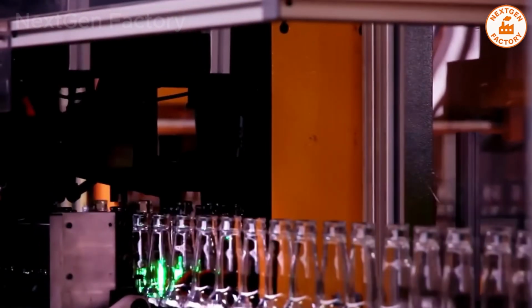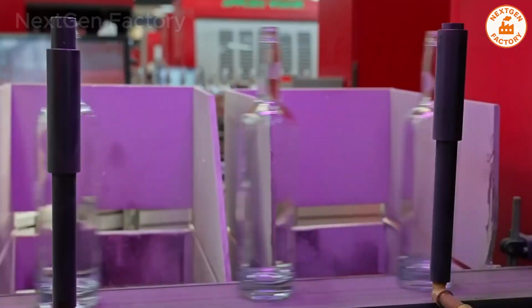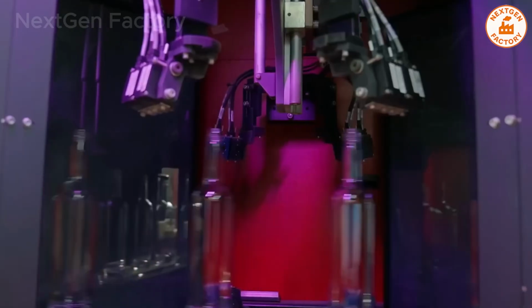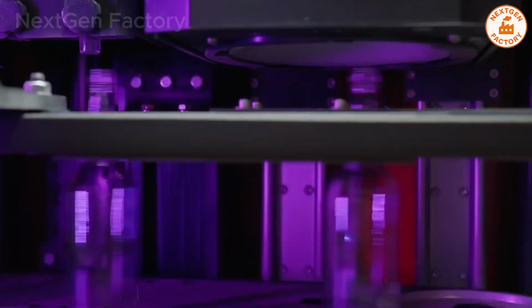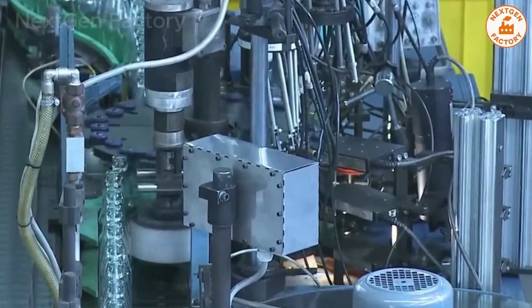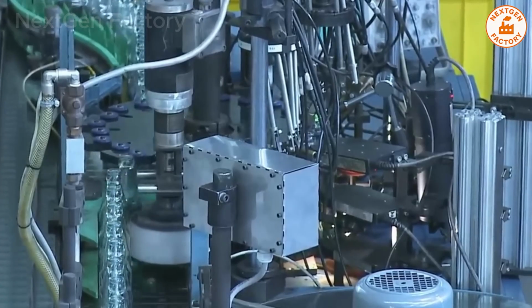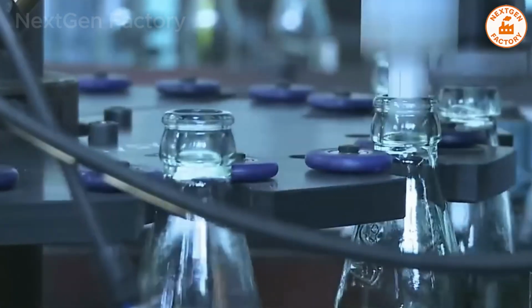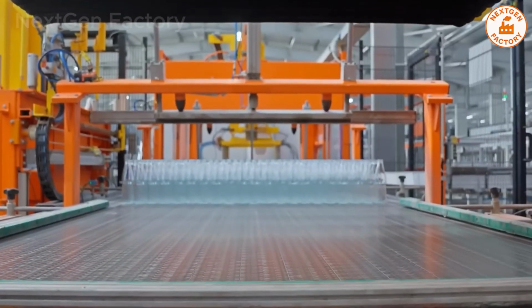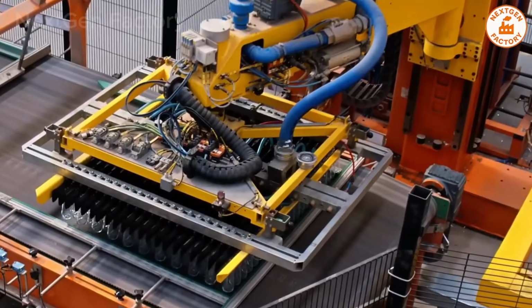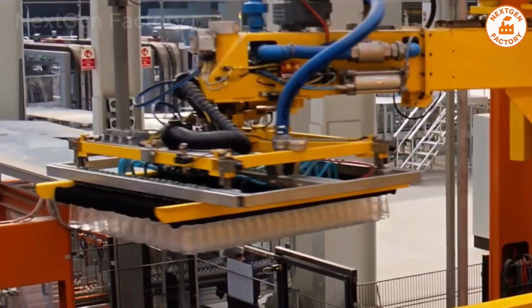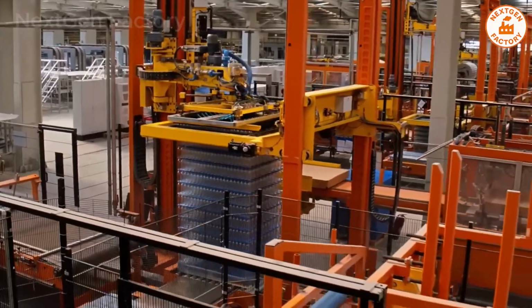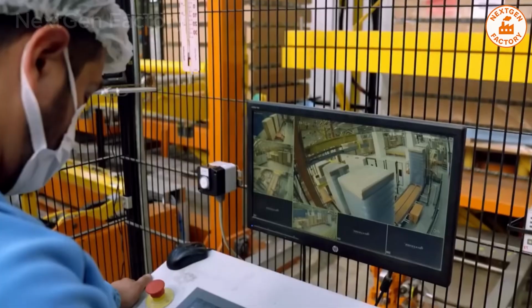Once cooled, the bottles enter the inspection line. High-speed cameras and laser sensors scan every millimeter of the surface. Algorithms detect bubbles, cracks, asymmetry, wall thickness variations, and neck defects. Bottles that fail even a single parameter are instantly rejected and recycled. Quality control in the glass industry is among the strictest in the world because defects can pose safety risks, especially in pressurized beverage bottles or pharmaceutical containers.